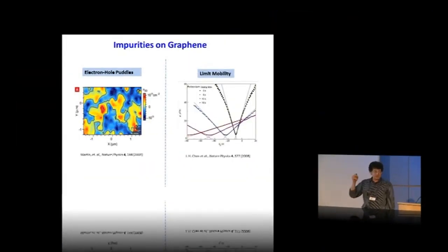But what we're really interested in is what happens when you modify graphene and what are the local properties of the graphene when you change it, when you manipulate its properties. One of the ways of doing that is to drop atoms and molecules on the graphene or to have impurities in the graphene. I just want to point out that we already know something about how graphene behaves when we add adsorbates to it from previous measurements. For example, this is Amir Yacoby's measurement using scanning SET, and you can see the electron-hole puddles that arise due to impurities derived from the silicon oxide layer.